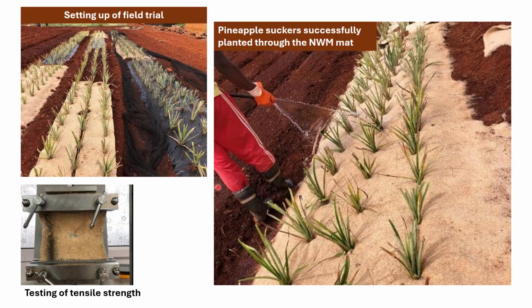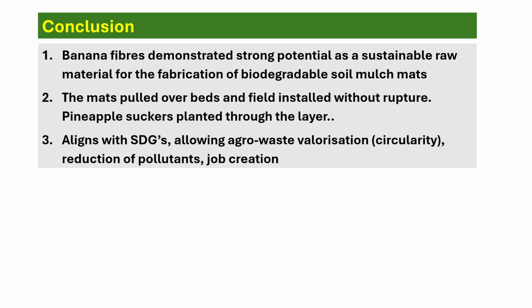The final mat was tested to see if it is according to certain international norms, and also we set up the experimental plots. As you can see here, they were successful in setting up the plot. Now the plots are growing, and we hope to see the results soon. So in conclusion, I can say that even though banana fibers are known for their stiffness, we were able to produce a 100% non-woven banana mat, which shows that locally available banana fibers can potentially be used for the development of soil mulches. And in this study, the mulch was successfully laid in the plantations. They did not rupture, and we successfully established our plantations. So it aligns with all the SDG goals.